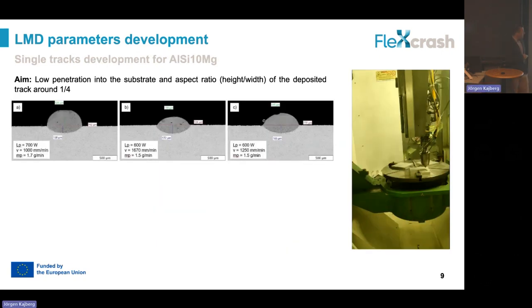Here you can see some initial tracks that we deposited with different process parameters, and you can appreciate the ratio between the height and the width of the tracks that we deposit. This is really important for us to control, where we usually want a height of 1/4 or 1/3 of the width. This is not a made-up value, but because we found in the past that if we develop the tracks in this way, we are able to make 3D shapes with low levels of porosity.